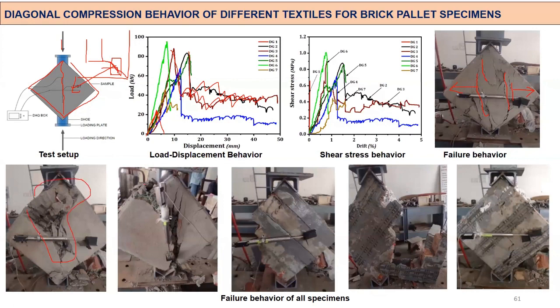And another grid, this is the polypropylene based grid. And when we use FRP, as already mentioned, the model is very good. FRP will give you wonderful strength. You can see the strength of FRP is tremendous, like fivefold increase, but the failure is sudden. So here also, we have used the same geogrid in the form of FRP with epoxy. So again, it is a brittle pattern.